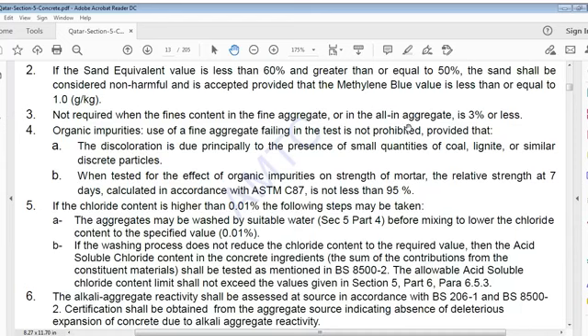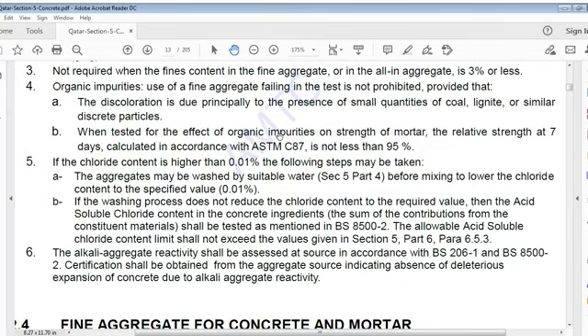Organic impurities: use of a fine aggregate failing in the test is not prohibited provided that discoloration is due principally to presence of small quantities of coal, lignite or similar discrete particles. When tested for effect of organic impurities on strength of mortar, relative strength at 7 days, calculated in accordance with ASTM C87, is not less than 95%.